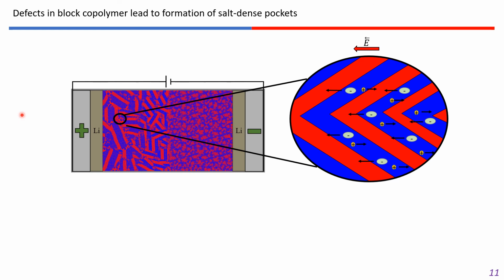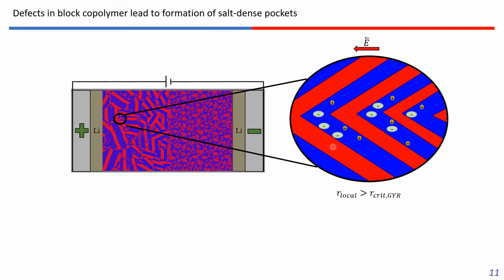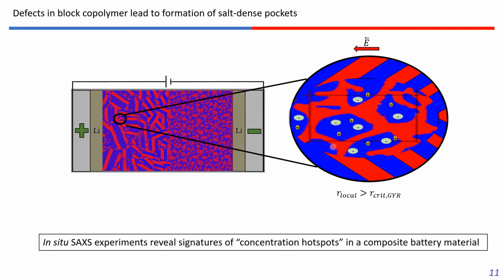So we'd like to propose a mechanism for how we observe these pockets of gyroid phases based on the three-dimensional structure of the block copolymer electrolyte. If we consider a defect where the insulating polystyrene domains block the flow of ions in the direction perpendicular to the electrodes, we can imagine that application of an electric field will result in accumulation of salt in this defect site, and if this local salt concentration at this defect exceeds the critical value needed to maintain the gyroid, then we can observe a phase transition to the gyroid morphology. And because defects aligned in this way are likely to be relatively rare, we only see a few pockets of this gyroid morphology emerge. And so our in situ SAXS experiments have revealed signatures of concentration hotspots, or local regions of increased salt concentration, which can form in a composite battery material.